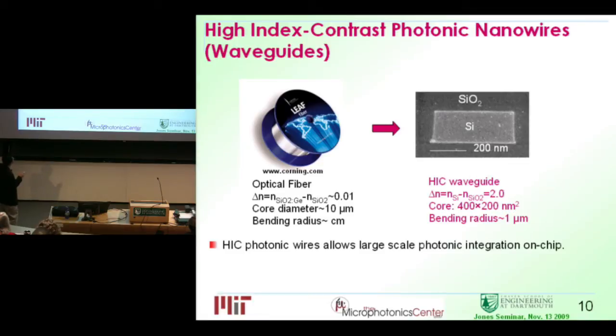So your core has to be large. It's 10 microns. And you cannot bend it very sharply because then the total internal reflection condition is not met, and the light will leak out. So to miniaturize your photonic wire, we're actually using silicon as a core and silicon dioxide as the cladding. The index difference is very large, so that you can make a small core device. This is sub-micron, or at the nanometer level. Many of my colleagues call this a photonic nanowire. This allows a bending radius of about 1 micron.